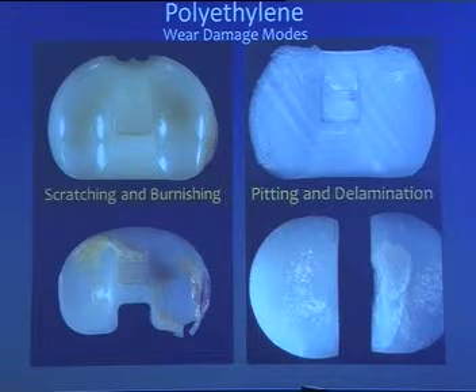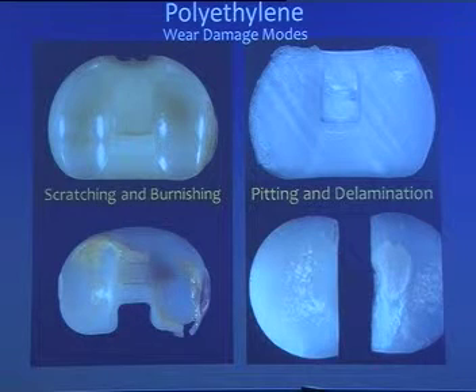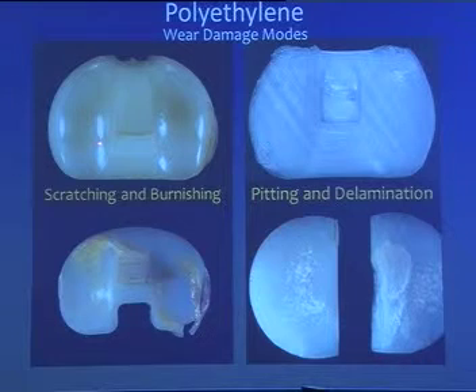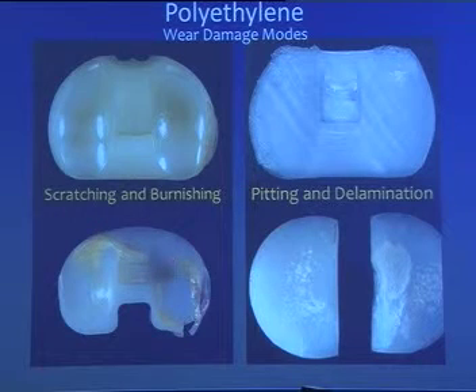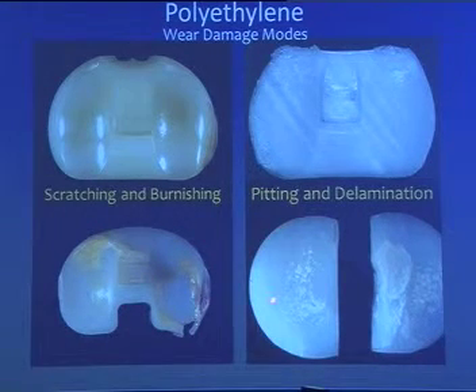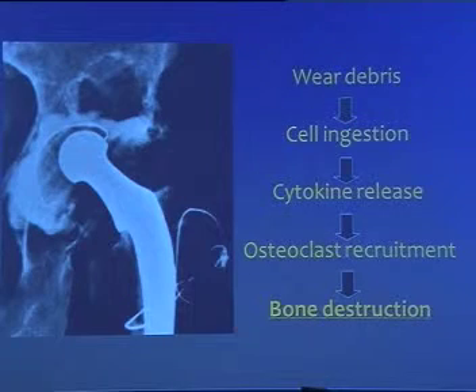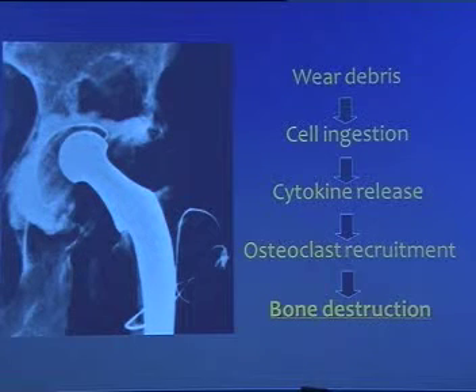Very quickly to show you the wear damage, this is a good polyethylene tibial insert taken out from the package. And as you see, you can move, and these are the words that we use: scratching, burnishing, pitting, and delamination. And again, the wear debris gets ingested, releasing cytokines, osteoclastic recruitment to remove this debris, and finally resulting in bone destruction.